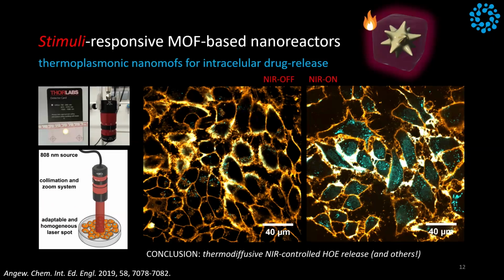In orange, you see the membrane of the cells, and then you can see that you have some cyan dots. These are the nanoparticles. Okay, this is the MOF, where you have the weak fluorescence of the cargo that we put inside of the MOF. Then I put some light, and I could release the dye from the cell. So my idea was working there.